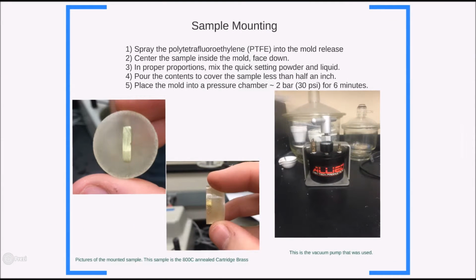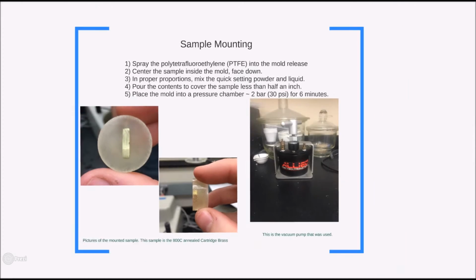Sample mounting. Spray the PTFE mold release located on the inside of the reusable mold. Center the sample inside the mold, making sure the sample is placed face down. In proper proportions, mix the quick setting powder and liquid. Pour the contents into the mold, covering the sample less than half an inch. Place the mold into a pressure chamber under 2 bar pressure for 6 minutes.